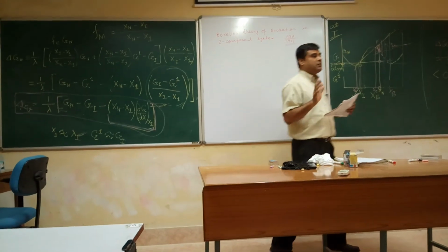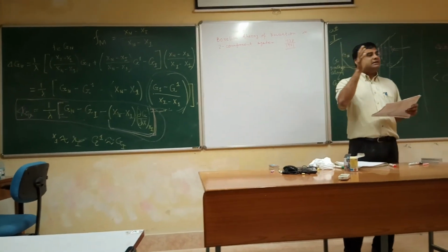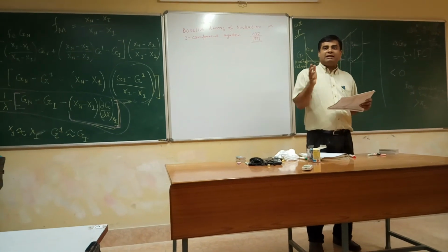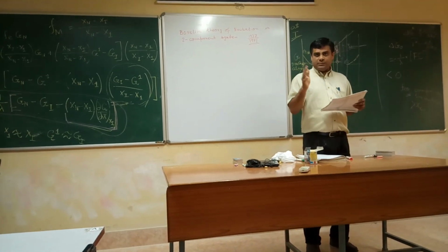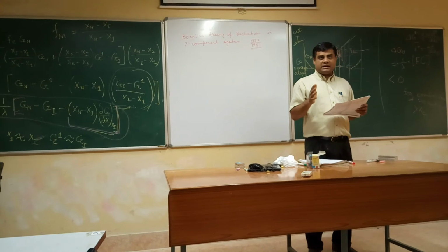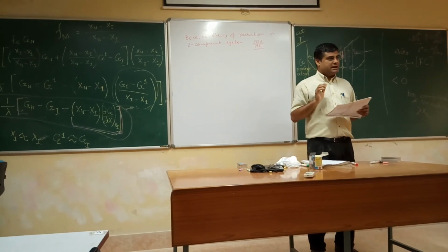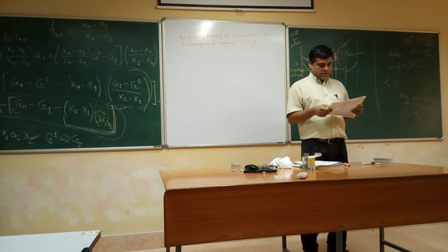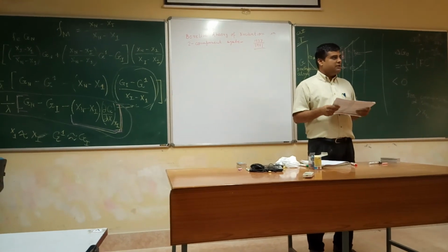So gamma also was neglected because he assumed the embryos are of fixed size, and he tried to see, through his model, for what fluctuation it will give the maximum nucleation rate, for a fixed size of critical nucleus. So gamma is not coming into the picture.